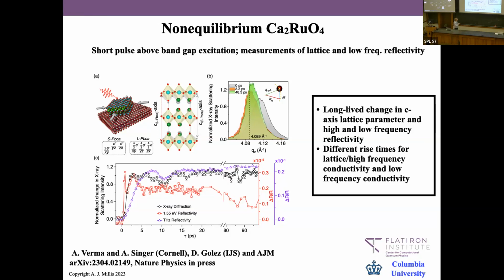Okay, now here's what happens to the lattice. They look at a particular X-ray scattering peak, in fact the 008 peak, which is connected with the C-axis lattice parameter. So what you see is that before irradiation, this peak is here. After irradiation, the peak moves down in reciprocal space, meaning that the lattice parameter is getting longer. And it goes back, in fact, to the lattice parameter you would expect in the high temperature metallic state.